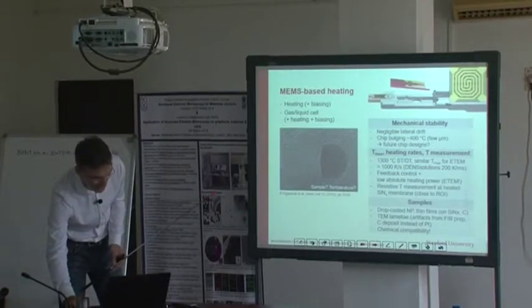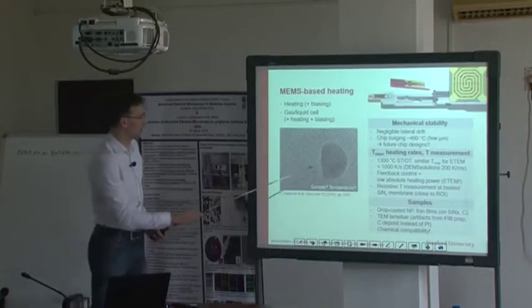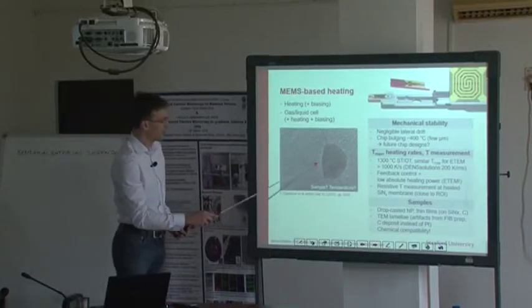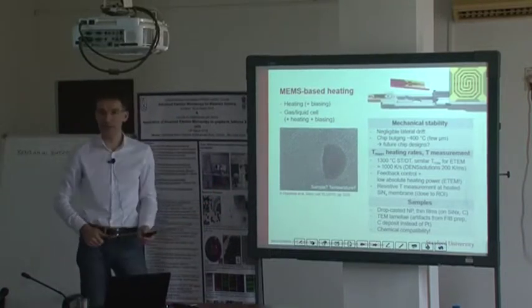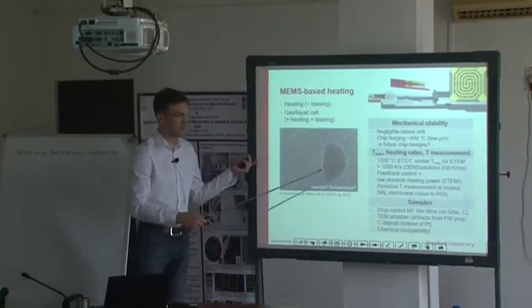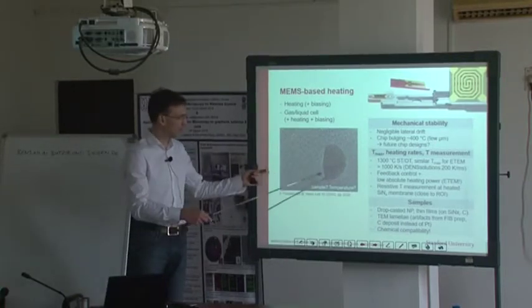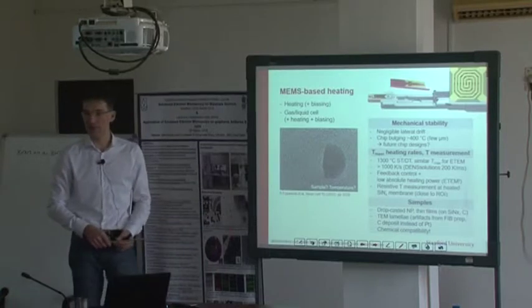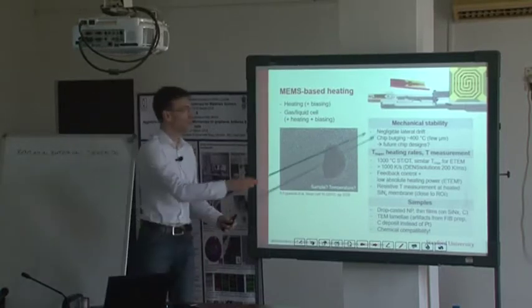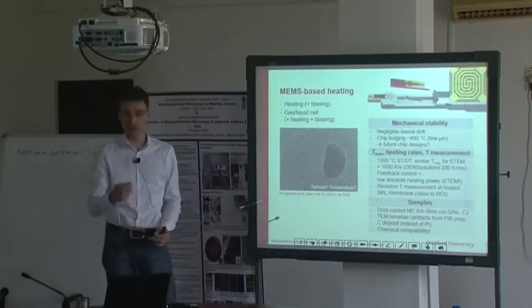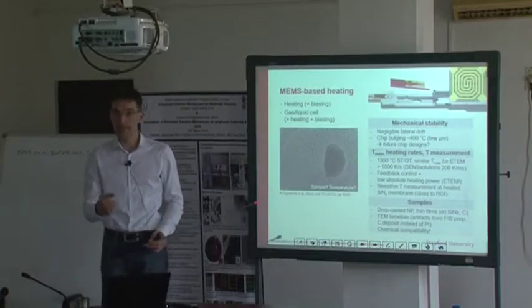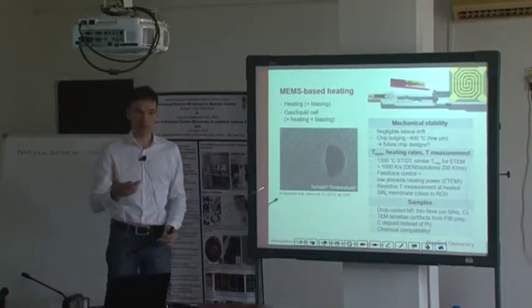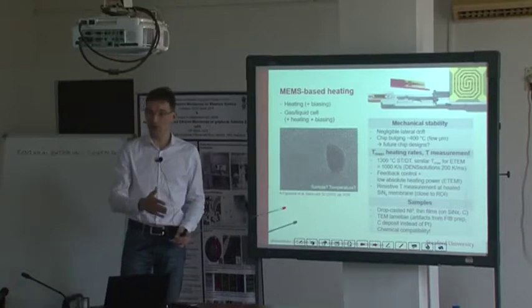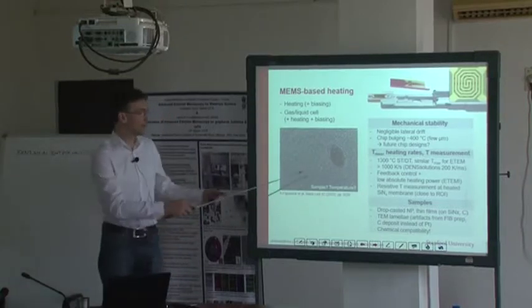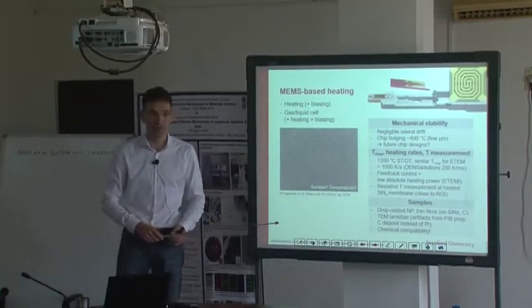On the left-hand side, there is another example of the recrystallization of a nanostructure on the atomic scale, and you see that there is hardly any drift. So this is atomic resolution imaging. You get a static image. You don't have any drift of those samples. This is the big advantage of using such MEMS-based heater chips, because you heat on a very localized scale. The evolving heat and radiation at high temperatures is strongly reduced, so you can do EDS at temperatures far above 800 degrees Celsius.